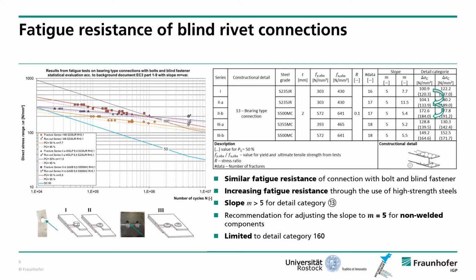And if we now use a high-strength steel inside the joint with blind fastener, the fatigue resistance increased from 104 to 172. So there is a direct link between the used material strengths and the fatigue resistance of the joint. And also for the configuration with 2 blind fasteners inside the joint, we can see there's an increasing fatigue resistance. As I already mentioned, the slope clearly deviates from the normative slope m equal to 3. So we recommend that for non-welded components, a constant slope of m equal to 5 should be used.